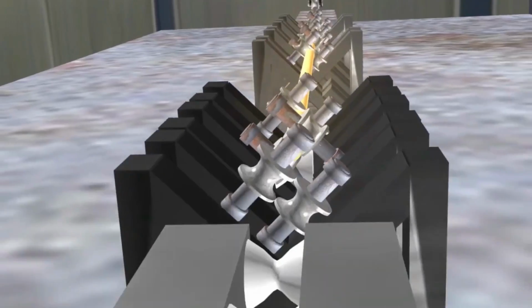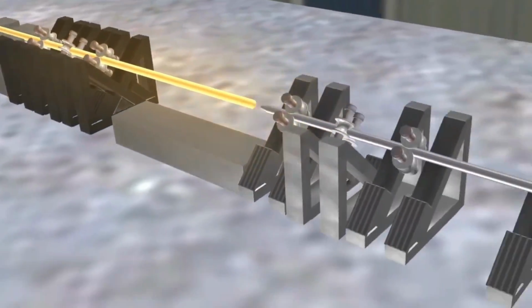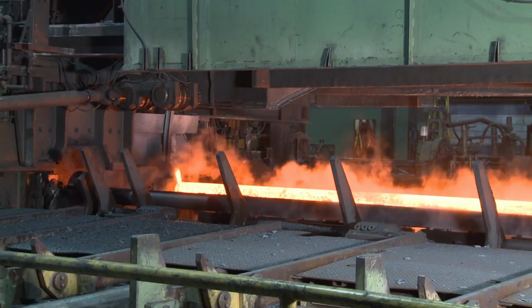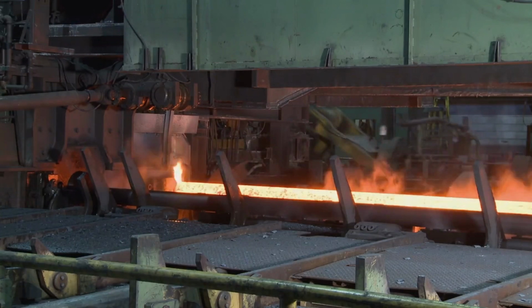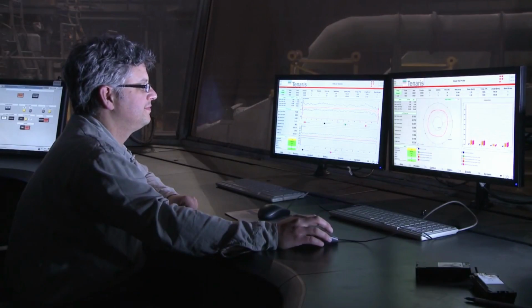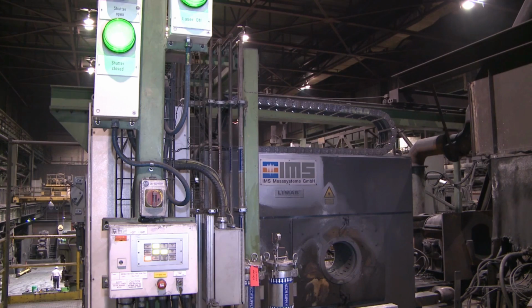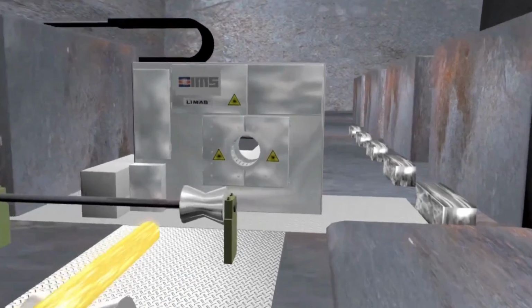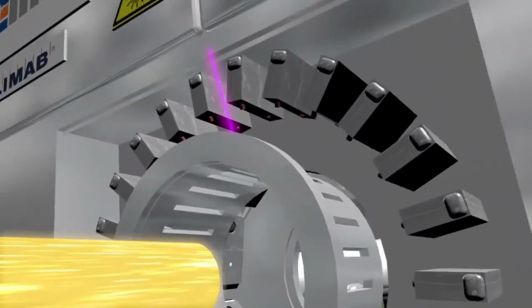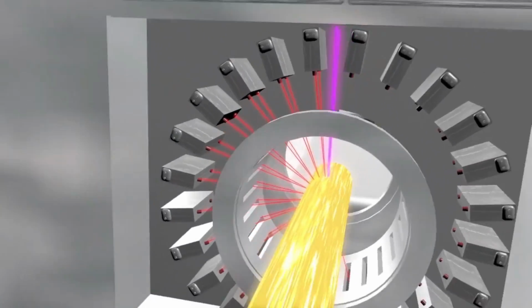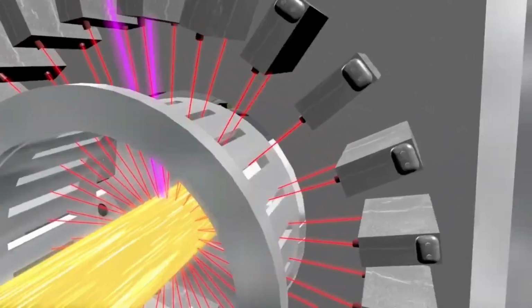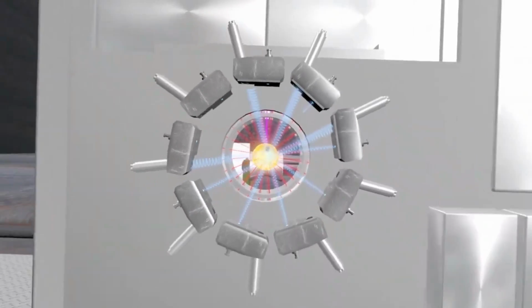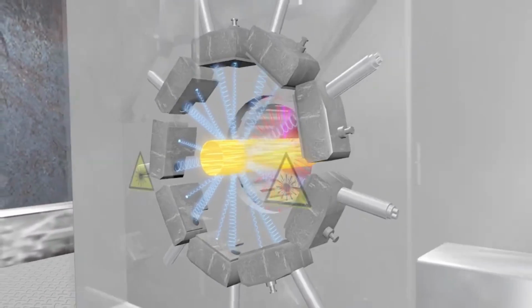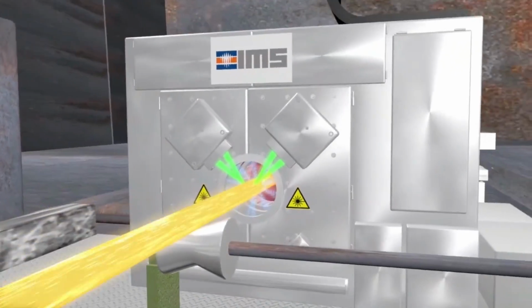A mill extractor then decreases the tube's outside diameter further as it extracts the tube from the mill while the mandrel is withdrawn. The pipe now enters a wall thickness gauge where it is scanned by 24 laser beams. The laser beams are triangulated off the pipe surface and provide 12 separate outer diameter measurements. Additionally, there are 9 separate radiographic beams that intersect the pipe to give mill operators 9 separate wall thickness measurements over the length of the pipe.